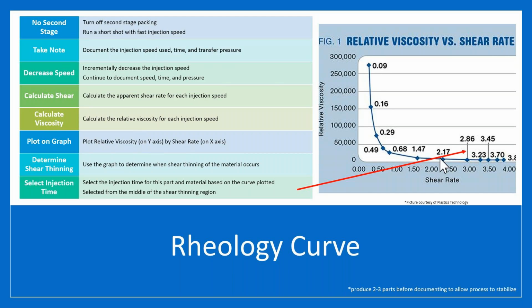And we can look at this, and if we come back up the curve and say we were to pick a shear rate somewhere in this region, and we had a small change to the shear rate, well, that small change to the shear rate, due to material variation, due to process variation, would kick our viscosity up a significant amount. If we're processing over here where the curve flattens out, you can see that a small change to the shear rate leads to a relatively negligible change in the viscosity. That's where we want to end up processing from a repeatability standpoint.